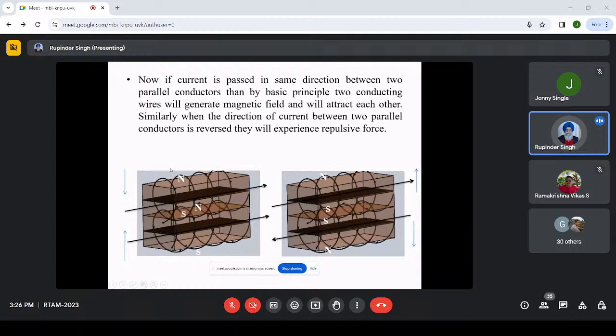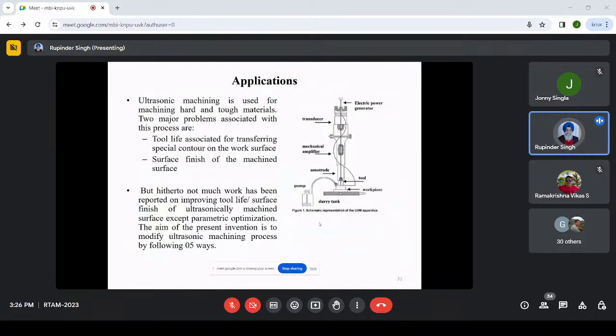So we have a north-south over here, and on the lower layer also there is a north and south. This north and south will attract each other, so there will be contraction. Then we change the direction of the current, so there is south and south, and there is a repulsion. So contraction, repulsion, contraction, repulsion. This is simply a transducer. So we were able to print a transducer using a simple concept of conducting and non-conducting layers.